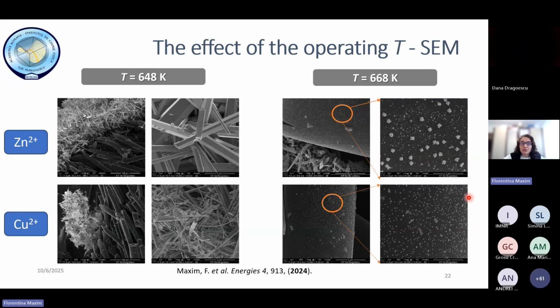From the SEM images, we can observe that there are different growth mechanisms related to the temperature of impregnation. So in the liquid-like state of water, we have only one-dimensional zinc oxide or copper oxide materials formed, but not attached, let's say, physically attached on the fibers. But in the gas-like state of the water, we have the real impregnation. So we managed to obtain nanoparticles of metal oxides deposited on the fibers of the carbon support.